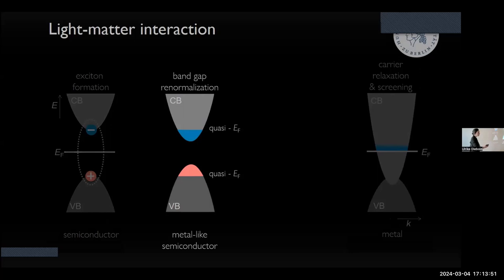Those free carriers also contribute to the screening in the system, reducing the Coulomb interaction between electrons and holes. And the theorists in the room, the DFT people, know this enhanced screening then leads to a band gap renormalization, because the Coulomb interaction is reduced and the band gap becomes smaller. While we have these carriers in the bands, we can speak of a metal-like semiconductor. You will see a Drude response in terahertz spectroscopy, for example. The thing is, it is still a semiconductor because the equilibrium Fermi energy is in the band gap.